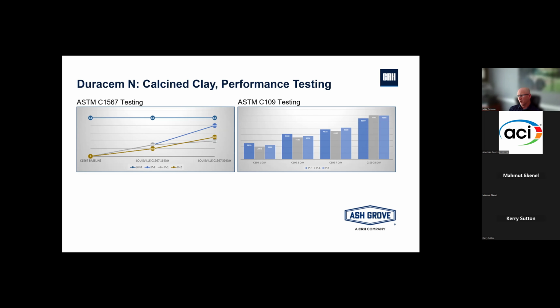And then from a strength development standpoint, as you can see, very similar here with the bars. So the dark blue bar is our Duracem F, and then the other two bars, the gray and the light blue, are two iterations, our 30% and 35% calcined clay products. As you can see, they perform right in line, a little lower on the early days, but then it catches up rather quickly, and by 28th day, it exceeds what we were seeing with the Duracem F product.